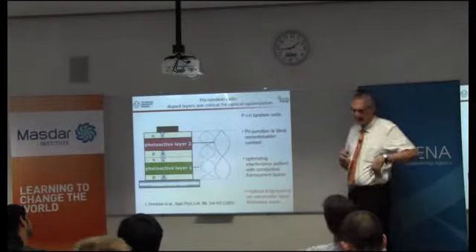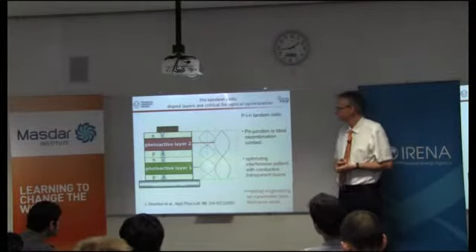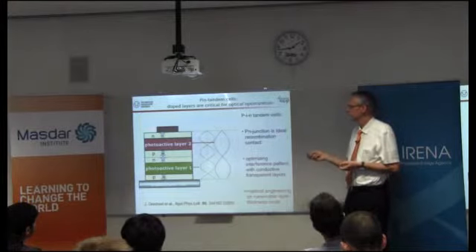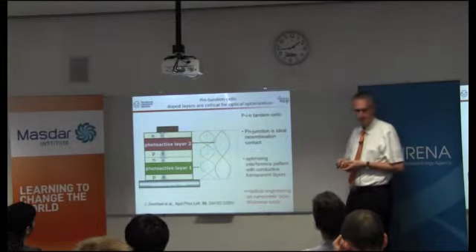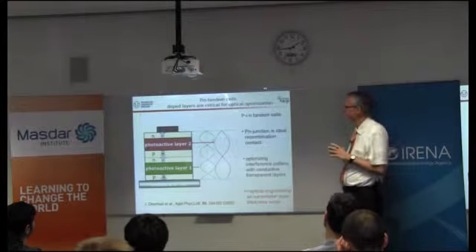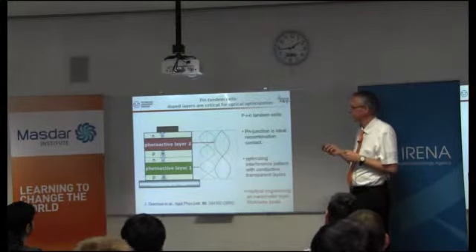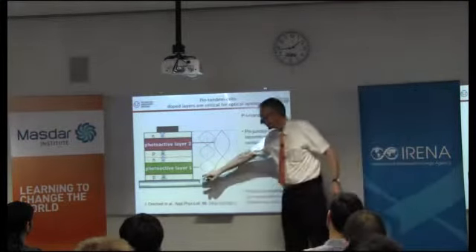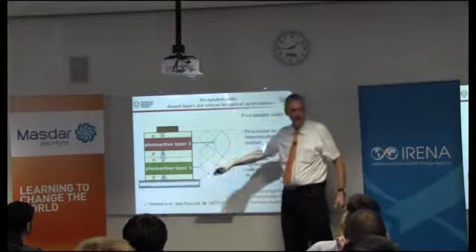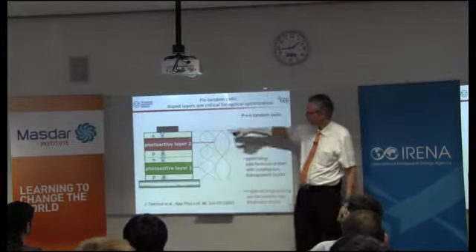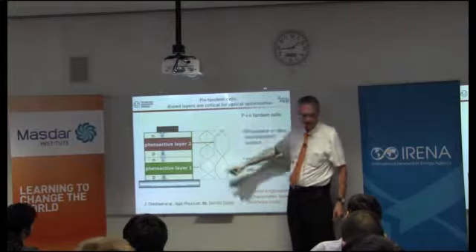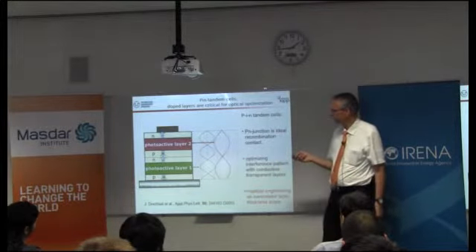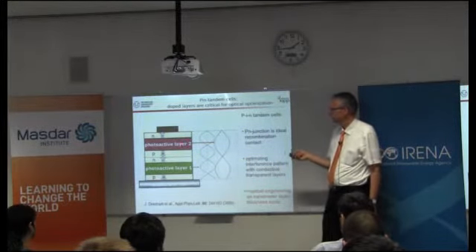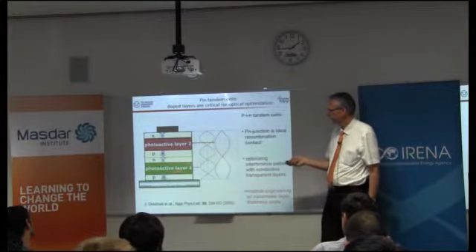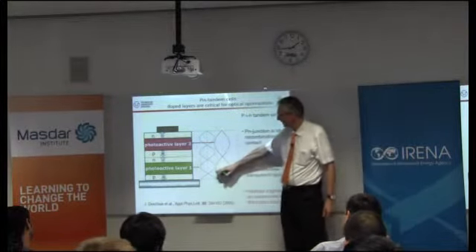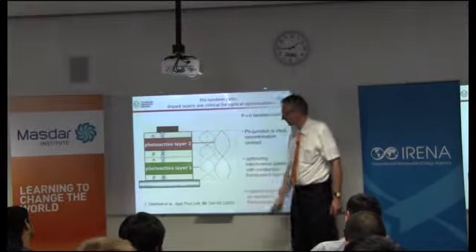So tandem cell, as said, means that we stack two junctions with different absorption on top of each other. And for organic solar cells, this is a little more complicated because the total thickness of organic solar cells is a few hundred nanometers only, which means that you have standing wave optics in the device. And you need to think about what you do, because you need to move your photoactive layers into the regions where the electric field is as high as possible.